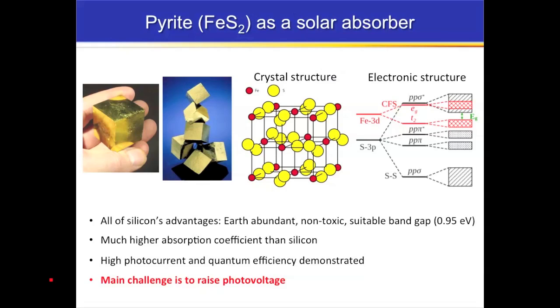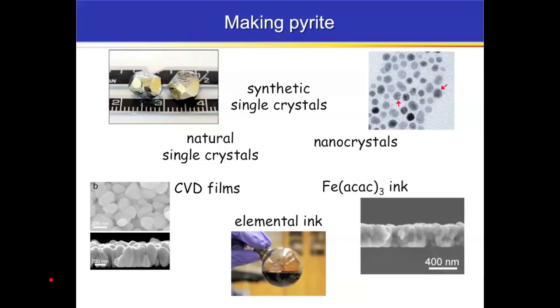The nice thing about pyrite is that it has all of silicon's advantages. It's earth abundant, non-toxic, and it has a band gap of around 1 electron volt, so it has almost the same Shockley-Queisser limited efficiency as silicon does. The nice thing is that it's a thin film PV material, so it has a much higher absorption coefficient. Demonstrated devices have shown very large photocurrents and high quantum efficiencies. The big thing that trips up pyrite is the voltage. The photovoltage is quite small in all devices that have been demonstrated to date.